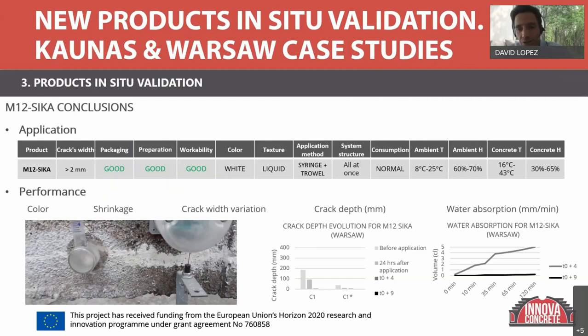In the case of the water absorption, for example, we used the Karsten tube in this case, not the SUSI test that Cristiano was mentioning. And here at T0 plus 4 months, we had a problem that we couldn't seal the Karsten tube properly to the concrete, and that is why we had a problem of water absorption highlighted there. But as you can see, after 9 months, it worked beautifully. So we can say that this product was working properly, and it didn't present any shrinkage problems.